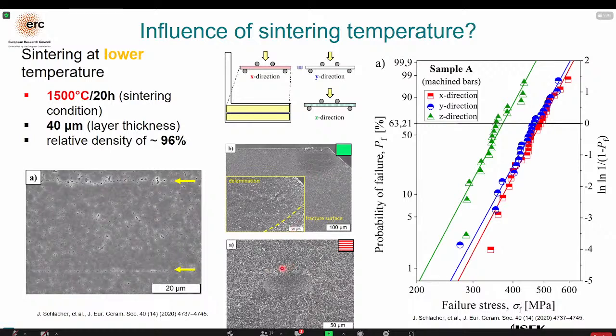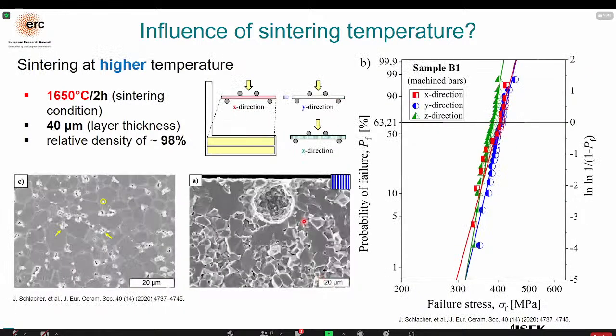And at different locations, we can find such pores which are trapped between layers. In the sample sintered at higher temperature, we can see a more homogeneous microstructure, which means that a lower amount of porosity is here, and so there are no layers visible anymore. Most of the fracture origins were some small pores directly located at the surface. Therefore, there is no difference in the strength in the different printing directions, so they are very similar. And we can also notice steeper lines, which means a higher Weibull modulus and a lower scatter due to the uniform fracture origins.